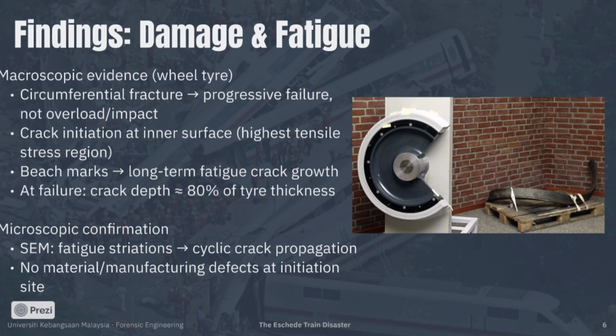Microscopically, fatigue striations confirm stable cyclic crack propagation, and importantly, no material or manufacturing defects were identified at the initiation site. This supports a service-induced fatigue process rather than a production flaw.